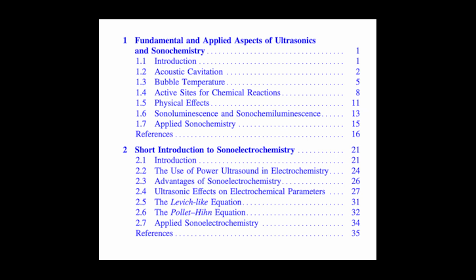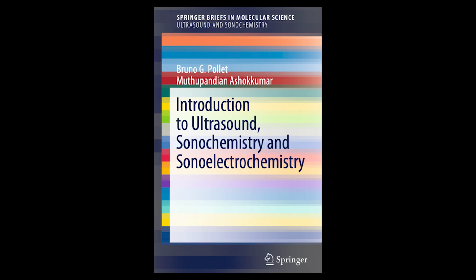So why does it shift under ultrasound? The sources suggest a couple of main reasons. One possibility is chemical irreversibility introduced by those reactive hydroxyl radicals. If the radicals react with the electroactive species or its products near the electrode, it can change the overall reaction pathway and shift the potential. Okay, side reactions changing things.